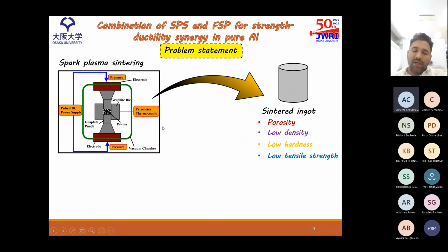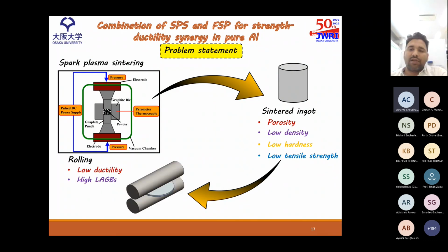Another problem with spark plasma sintering is that the grain size is very high because of the long exposure to the higher temperature. So due to this higher grain size, the tensile strength is further reduced. So the most prevalent solution is to subject these powder metallurgy components to some kind of severe plastic deformation process like rolling or extrusion.